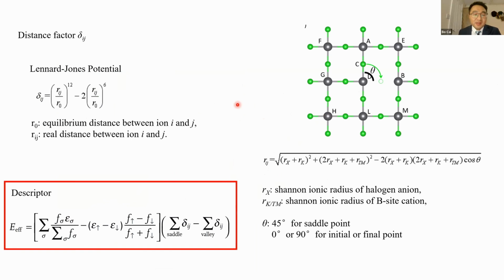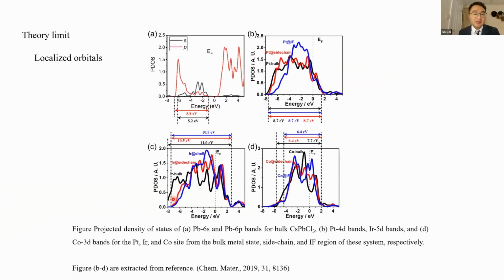Then, combining two aspects, we extracted descriptors. This section is related to the electronic density of states. That means decreasing the mismatch of band centers would increase the migration barriers, EB. Does this theory work well for halide perovskites?